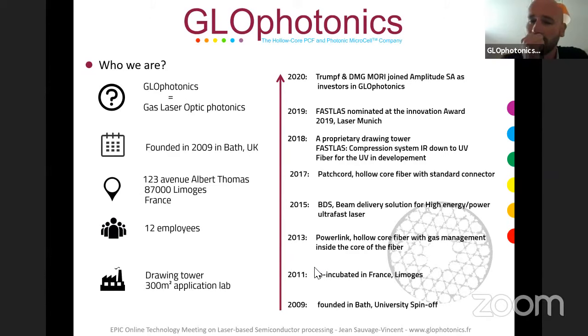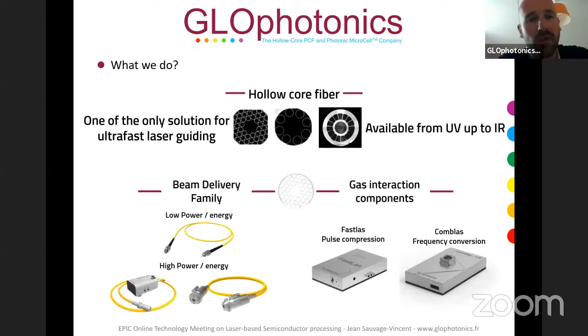So what we are doing, basically we only make optical fiber. We do have a drawing tower. It means that we are able to make the fiber on our own. What is optical fiber? Basically, if you compare a classic silica fiber to our optical fiber, a classic fiber is a silica fiber surrounded by another silica component. The core of the silica fiber has a high refractive index, and so you can guide light through a fiber. But the problem with the classic fiber is that if you increase the energy and peak power of a laser and inject it into this fiber, you will damage it, you will break the fiber, definitely.